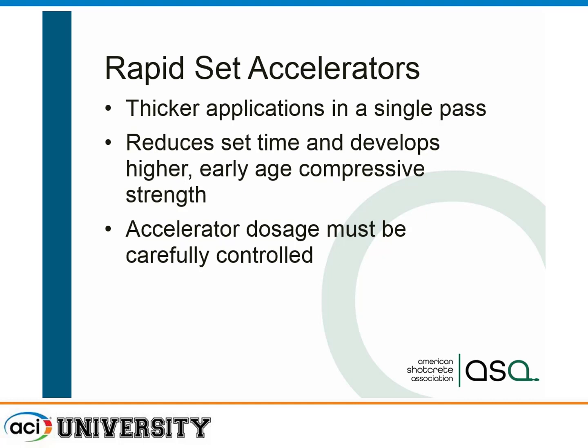Another thing we can do with shotcrete, we can use alternative cements. I'm not showing it up here, but we can use the very, very rapid set cements that can get us high early strength. Predominantly that's used in a dry mix application because what are we doing different in dry mix? We're not wetting it until it's right at the nozzle. So it allows us to use a lot of these alternative cements to get that concrete in place.